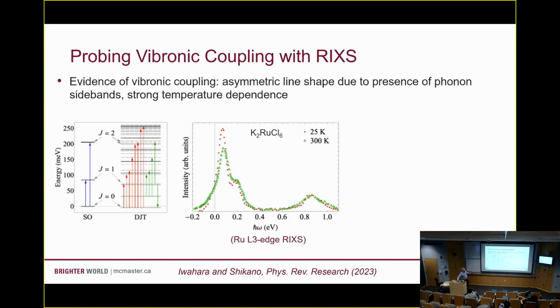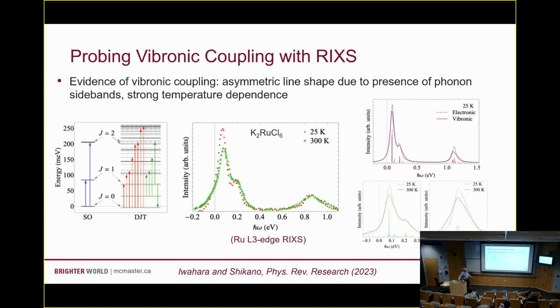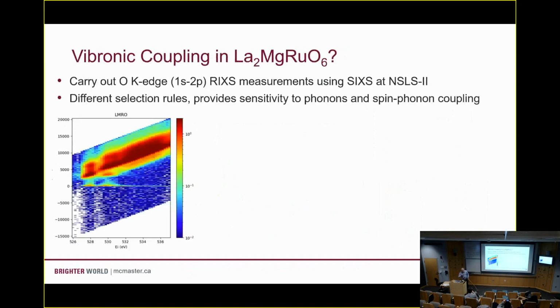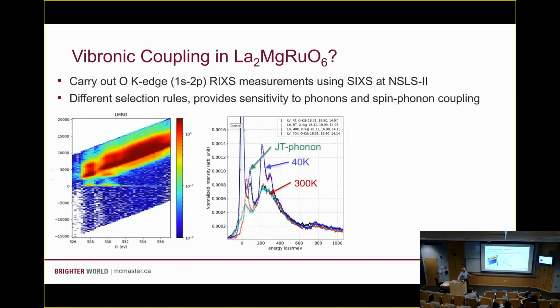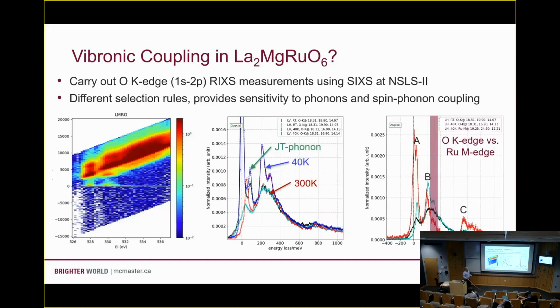And this is what's been seen in this other excitonic candidate, potassium ruthenium chloride. Okay? You get an asymmetric line shape, and it has strong temperature dependence. You can tease out what part of this line shape is electronic and what's coming from the electron-phonon coupling, the vibronic piece. And you can see how that changes as a function of temperature. Right. And I'll just say when we do the same measurements on LMRO, we see with temperature and polarization dependence, a Jahn-Teller phonon mode here, and this asymmetric line shape that becomes more asymmetric at higher temperatures. And this is a signature again of this kind of vibronic coupling.